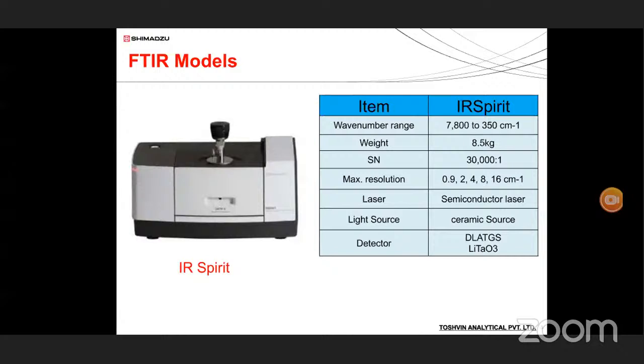And the FTIR beam splitter is made up of germanium-coated KBr. KBr is a hygroscopic material, so if the moisture or humidity increases, the beam splitter may break down. So the humidity factor plays an important role. We have to control humidity by using the dehumidifier, which is inbuilt in the instrument, or we can put silica packs at the back or on top of the instrument, where space is provided for all the instruments.